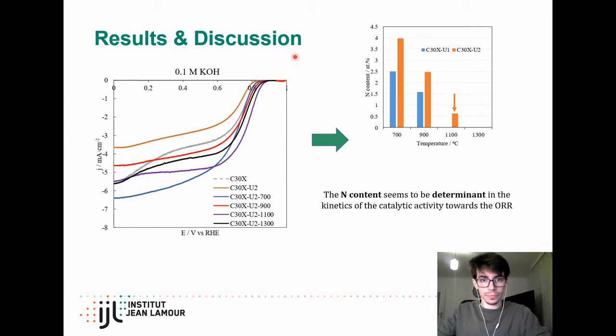On the other hand, the highest catalytic activity by using a carbon-urea ratio of 1:2 was reached at 1100 degrees, and this is because there is still nitrogen content above 0.5 atomic percent in these samples. After heat treatment at temperatures above 1300 degrees, there is a clear decrease of the catalytic activity from the purple line up to the black line, since the nitrogen has been completely removed after these very high temperatures.